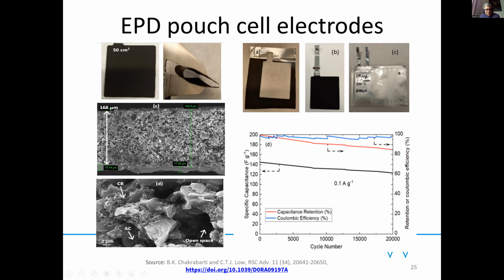But to maintain good performance at thick electrodes is quite a challenge, and this is something that we managed to show in this research. One reason is that acetone is a very volatile solvent. So while it evaporates off, it creates pore spaces within the activated carbon deposits, leading to good electrolyte